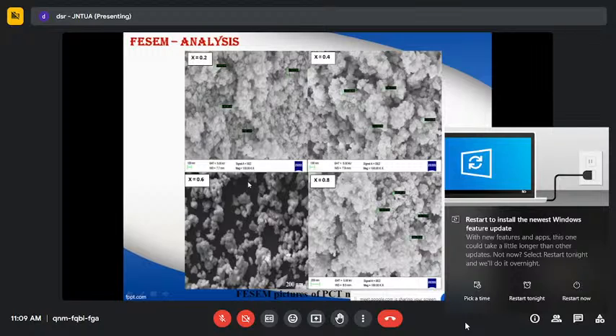From the images, it is evident that for all the samples, agglomerated PCT nanoparticles were formed, and also stone-like grains were observed. Especially for 0.6 cobalt content, the formed grains appeared almost in spherical shape. Here you can see the spherical shape very clearly. The grain size was observed to be reducing with rise in the cobalt content. You see here in the 0.2 concentration of cobalt, grain size is large, a bit decreased, and finally when cobalt concentration is 0.8, the grain size has been reduced considerably.